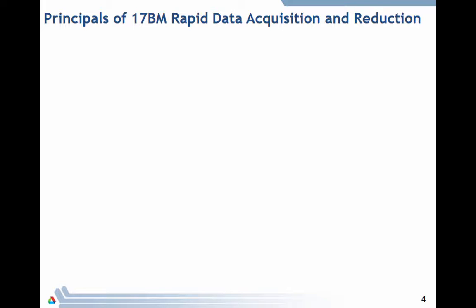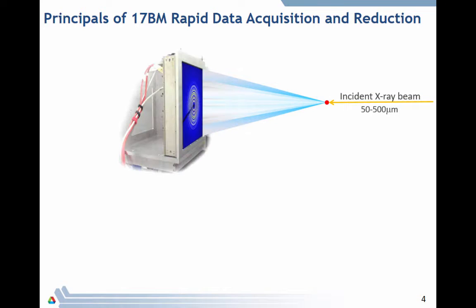Okay, but how do we collect the data? As you saw, we have an area detector. So what we pretty much do is shoot the X-ray beam at our sample and collect the 2D powder pattern via the area detector. Our X-ray beam size we usually focus to about 500 microns, and after that we can cut it down with a set of pinholes, which can be between 50 and 500 microns, depending on your needs.